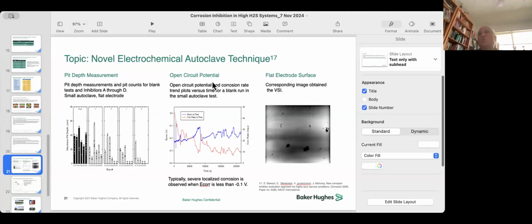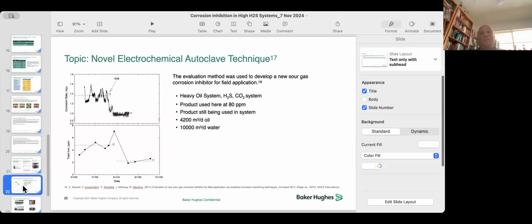This has not been developed so well, perhaps because my guy who did this also went to our competitor, but not many people are really looking at it. It's a real neat technique, but you have to know when the free potential changes and then record it. The beauty of it is that in situ you actually have a means of determining pitting and when pitting corrosion occurs, and that should be very valuable. We use that for one of these products, which has been used all over the world.